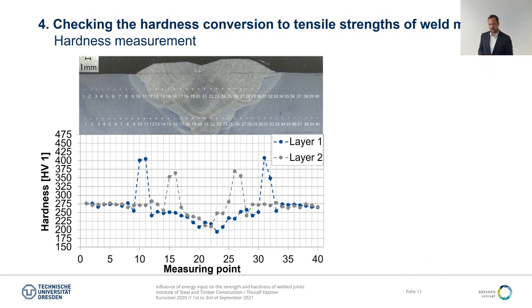So we also performed hardness measurements here in 2 layers. Layer 1 is the upper layer, layer 2 the lower layer, to have more information about the weld cross section at the end. And what we can see is that we have interesting points where we can also examine the influence of the upcoming weld layers.